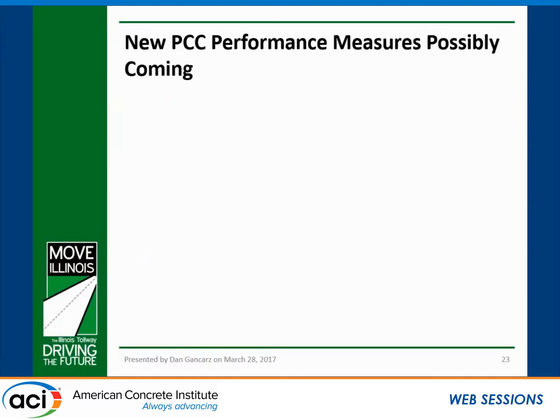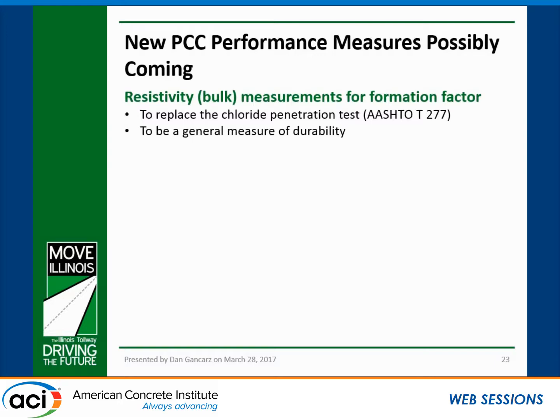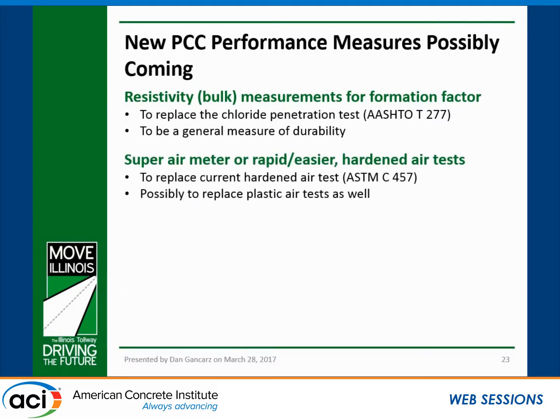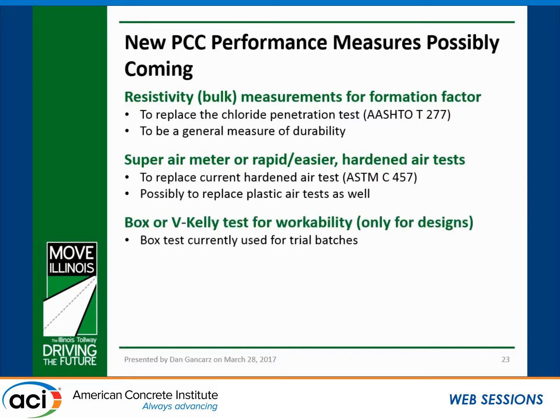So we're always looking to improve our specs, and some of the new performance measures we're evaluating include bulk resistivity for application of the formation factor. We're looking at this to replace the chloride penetration test and then looking at it as a general measure of durability. We're also looking at implementing the super air meter, possibly to replace current hardened air testing, and then also looking to replace plastic air testing with a super air meter requirement, which provides the total air and then your SAM number. We're also looking at the box or V Kelly test for workability during the trial batch stage. We're currently doing the box test on all pavement trial batches to evaluate the consolidation under vibration.